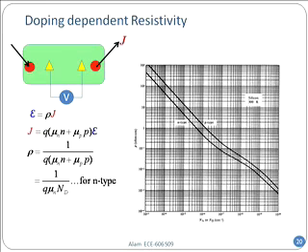So that is the plot on the right-hand side. That's what you see, the doping on one side. So they prepare a set of green samples of various doping levels, and they make the measurement of rho by measuring the current and the electric field. The electric field they obtain from the voltmeter by taking the voltage and dividing by the distance between the yellow probes. And from here, they get it.